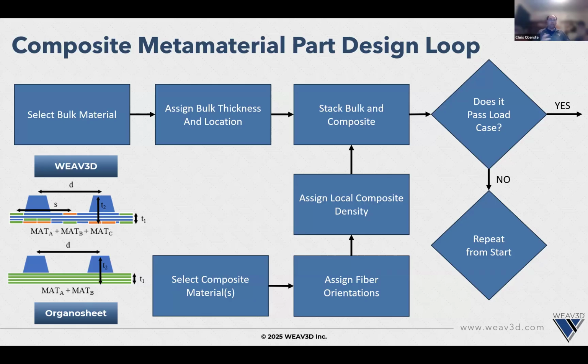At the same time, in parallel, you're going to decide what composites you are going to put in this design. So, is this going to be a constant thickness laminate? Is it going to be something like what we do, which is lattice structures? You're then going to have to determine what the fiber orientations are and how much composite you put in each area. So, if you have a total part thickness of 3 millimeters, do you do 2 millimeters of composite and 1 millimeter of bulk, or do you do it the other way around? And then that resulting stack up of the composite and the bulk will give you your final part thickness and part geometry, and then you'll test the load case.